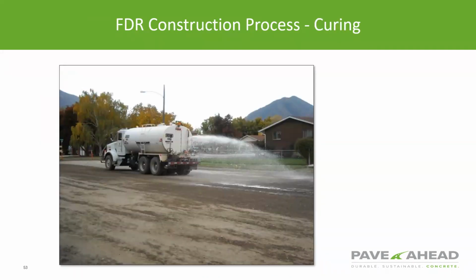And then some type of curing, typically. It could be wet cured with water, or you could cure with emulsion, because it's about trapping that moisture in, kind of like your bridge deck. You pour concrete on a bridge deck. What's the best way to cure concrete? Flood it underwater for like a month. So if you can keep it damp, you're going to get a better cure out of it. And it's this exact same thing with soils or FDR.